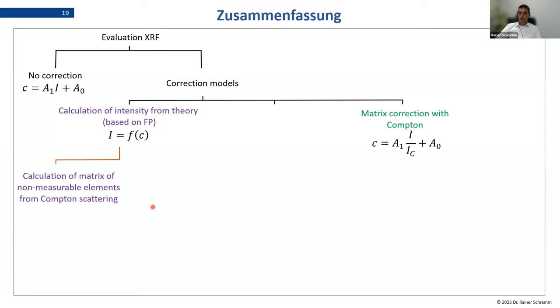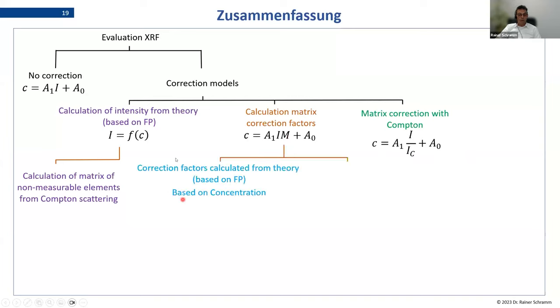On the other side, we have a pure empiric matrix correction, and there the simplest way would be to use just a Compton peak. So your intensity is just divided by the Compton intensity, and in this way you make a first sample matrix correction. Or you just want to do a real matrix correction, and this could be then based either on the theoretical approach. That means you let calculate your matrix correction based on the fundamental parameters, or you use standard materials to calibrate your matrix correction. And there we have the two models, concentration-based or intensity-based.